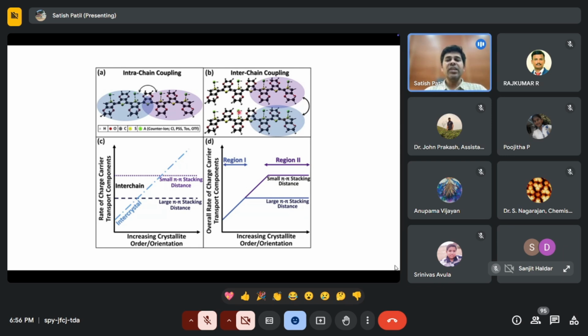So essentially, when the charge carriers move along this backbone of alternating double and single bonds, through this pi electron cloud, the charges will hop across the chains. So the transport mechanism in these kinds of materials is by hopping, not band-like transport. In a conventional semiconductor, you have very little disorder, whereas in this case, disorder kicks in by various means. For example, there is structural disorder, there is disorder due to chain conformation of the polymer, and there is disorder due to the weak inter- and intra-chain coupling. So there are numerous parameters which control the transport properties of these polymers, and as a result, it's very difficult to attain high charge carrier mobility.